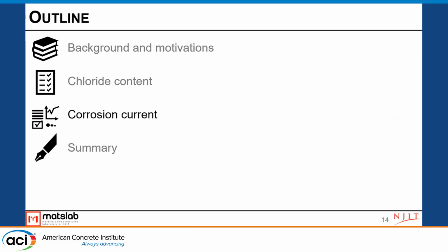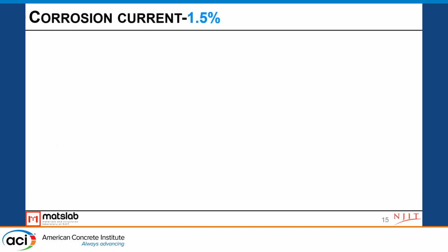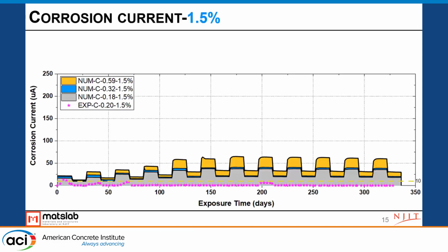So after we get the chloride distribution in the concrete, we can continue with the next step and conduct the corrosion analysis. The result we get here, first we are looking at is 1.5 surface concentration. So this is corrosion current versus exposure time. And we have different crack widths: first is 0.18 millimeter, second is 0.32, third one is 0.59.